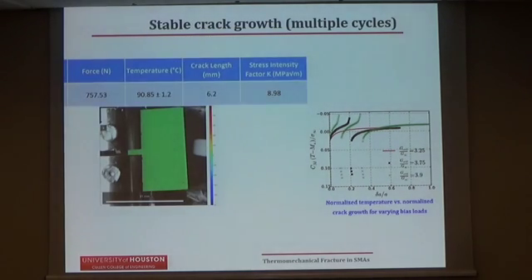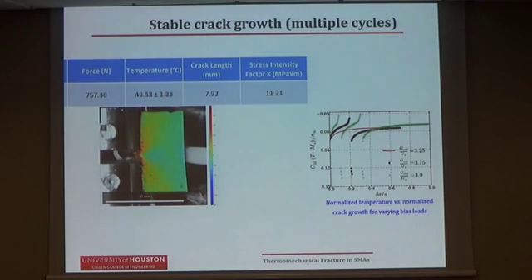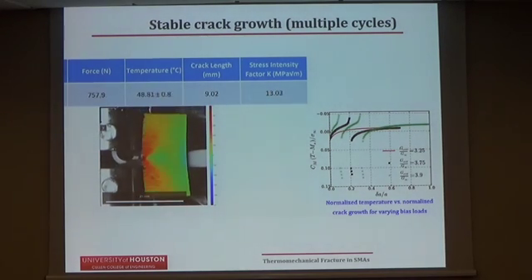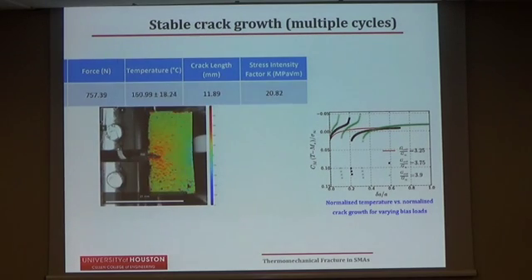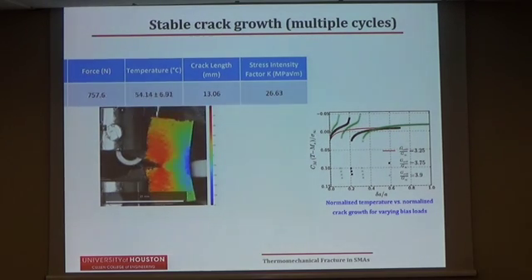I won't go here into the details. What I will say though is that depending on the applied load level, it is possible that the stable crack growth regime may extend into several cycles, right? So if I remember correctly, we needed 21 cycles to break this material. And the crack has started growing even from the first cycle.